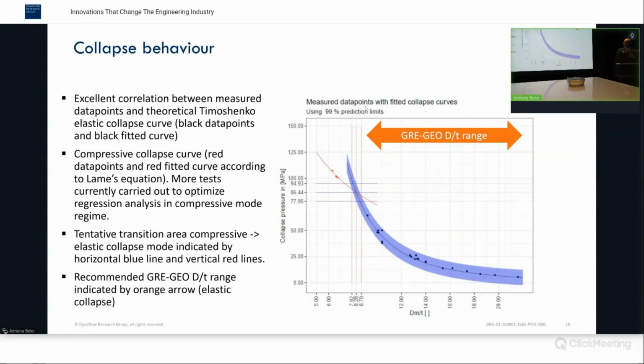So for this project and for the guideline, we decided to stick to elastic collapse. The reason is that, especially for the compressive collapse, we are not sure at which level failure will develop. You know what the ultimate is, but you don't know exactly at what level damage starts to propagate. The elastic collapse is more forgiving. It's an elastic type of failure mode.